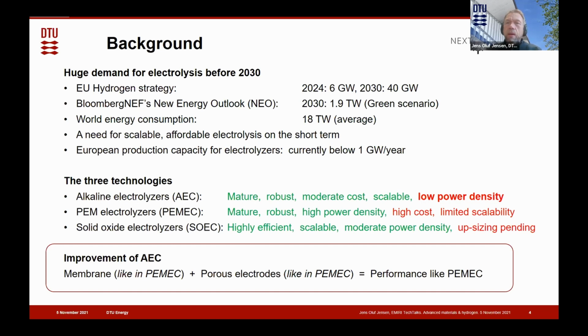So we believe that if we look at the problem with the PEM or the alkaline electrolyzer today, that's the low power density, which is actually a low current density at a reasonable voltage. So that's mainly a matter of internal resistance. And that boils down to the membrane, which is today a diaphragm, which actually works pretty well, but the internal resistance is higher than it should be.